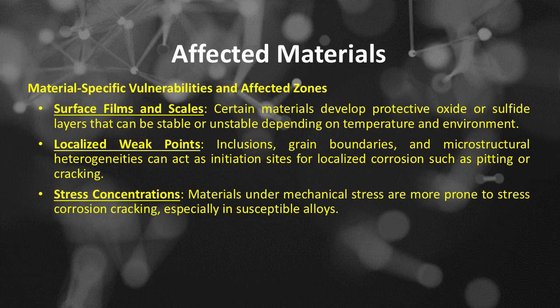Material-specific vulnerabilities and affected zones include, the first is surface films and scales. Certain materials develop protective oxide or sulfide layers that can be stable or unstable depending on temperature and environment. The second is localized weak points. Inclusions, grain boundaries, and microstructural heterogeneities can act as initiation sites for localized corrosion such as pitting or cracking. The third is stress concentrations. Materials under mechanical stress are more prone to stress corrosion cracking, especially in susceptible alloys.